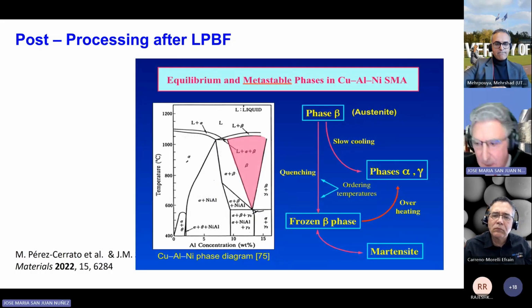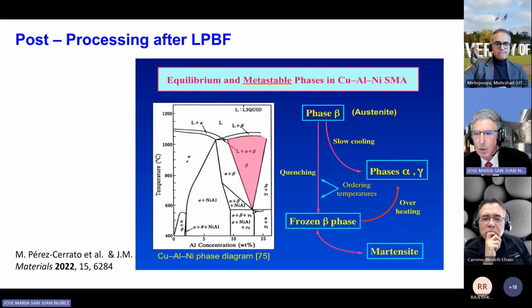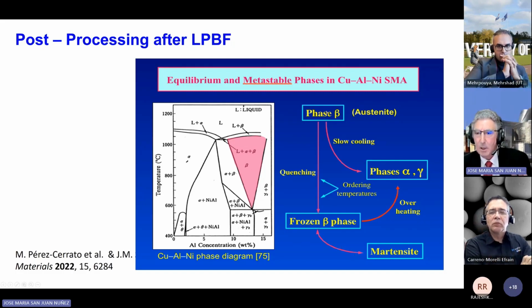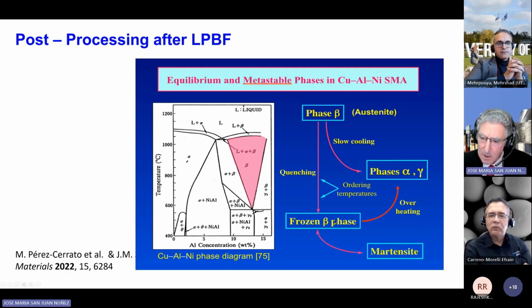To understand this aspect, let me show you the equilibrium and metastable phase diagram for this kind of alloy. So we start from the austenite at high temperature, a phase that has an equilibrium stability domain at high temperature, and then we have to quench this phase to be frozen at close to room temperature, more or less, and then the martensite transformation takes place at lower temperatures. So if this phase, austenite, is cooled slowly, it will decompose in the equilibrium phases. But what is more important for us is that if this frozen beta phase is overheated, it will also decompose in the equilibrium phases, because it's not an equilibrium phase at room temperature, or 100 degrees centigrade, at which we are using it as shape memory alloys.